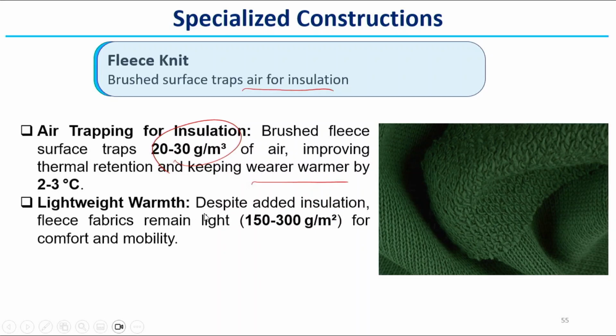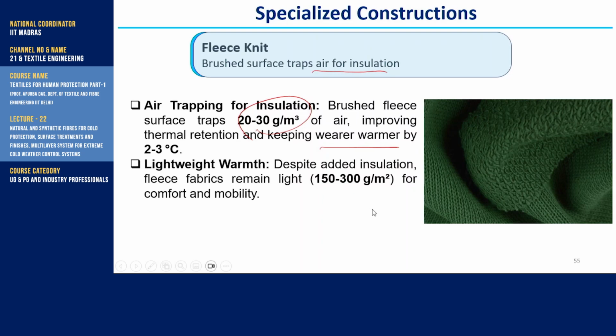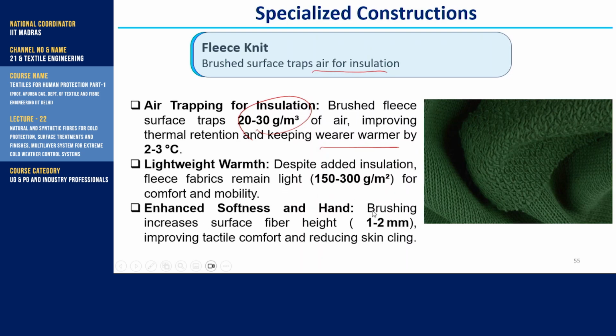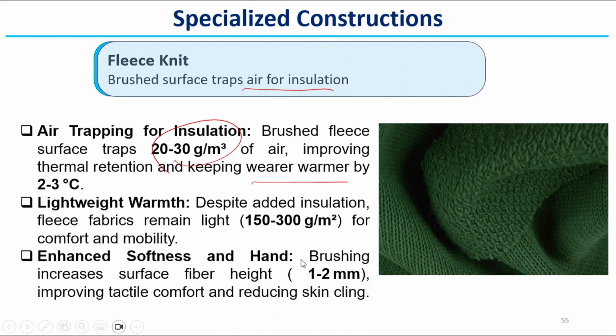Lightweight warmth: despite added insulation, fleece fabric remains light, 150 to 300 gram per square meter, for comfort and mobility. So, you can have lightweight, it gives warmth and enhances softness and hand. Due to the fleece structure, it enhances softness; brushing increases the surface fiber height by 1 to 2 millimeter, improving tactile and touch sensation.